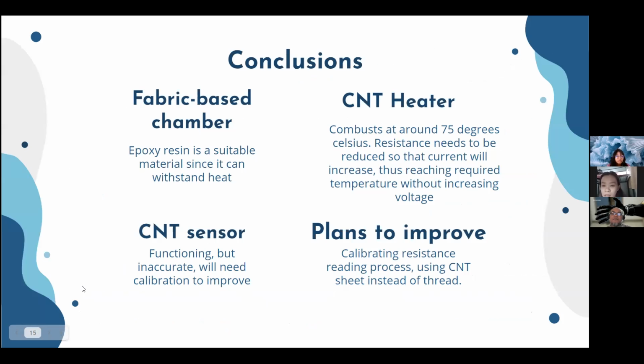Conclusion. So for conclusions, the fabric-based chamber, the epoxy resin is a suitable material since it can withstand heat up to 95 degrees Celsius. As for CNT heater, it combusts at around 75 degrees Celsius, which means that the resistance needs to be reduced so that current will increase and reach required temperature without increasing voltage that may cause overheating. For CNT sensor, it is functioning but inaccurate, and it will need calibration to improve the reading. Other plans to improve include calibrating resistance reading process, using CNT sheet instead of thread, and as I've mentioned before, using a different material to construct the CNT thread.